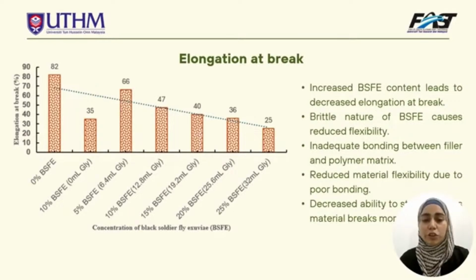Elongation at break measures a material's ability to stretch or elongate before breaking. This graph also shows that as the BSFE content increases, elongation at break decreases. This decrease can be attributed to inadequate bonding between the filler and the polymer matrix. This inadequate bonding results in decreased material flexibility and reduced ability to stretch before breaking.